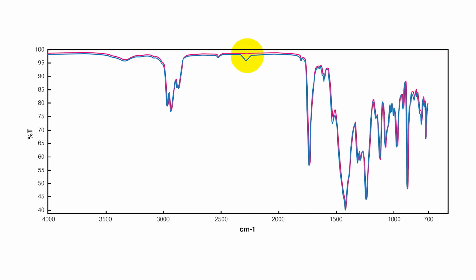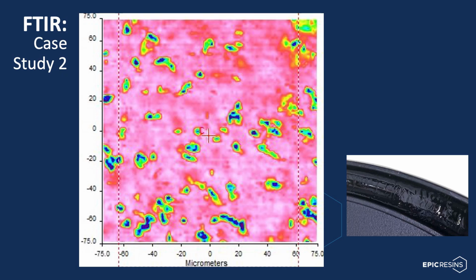This is an NCO functional group. NCO is the reactive component of the B side of this formula, and its presence in the FTIR shows that it is unreacted because it was not properly homogenized during the dispense process. In looking back at the FTIR array, the dots that are blue in the array are areas where the B side was not sufficiently mixed, and the pink regions are areas where sufficient mix was achieved.